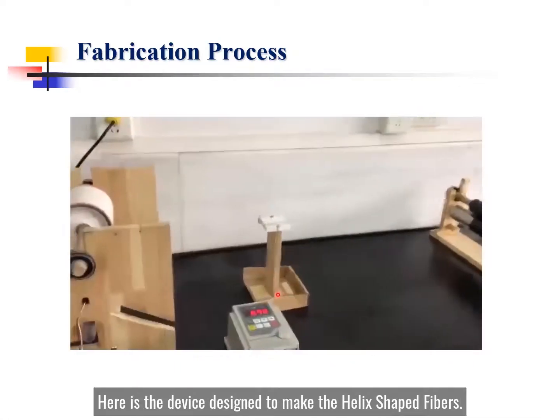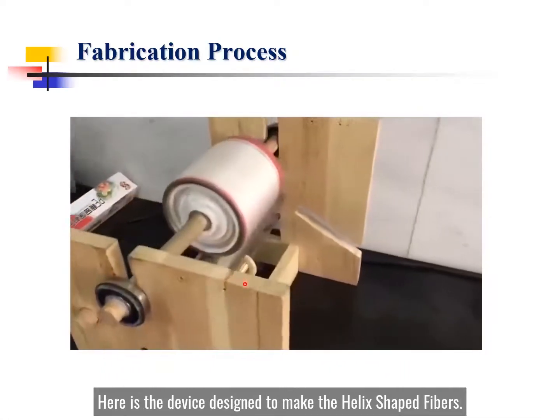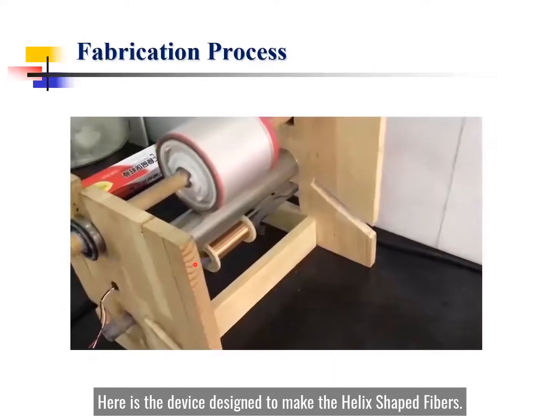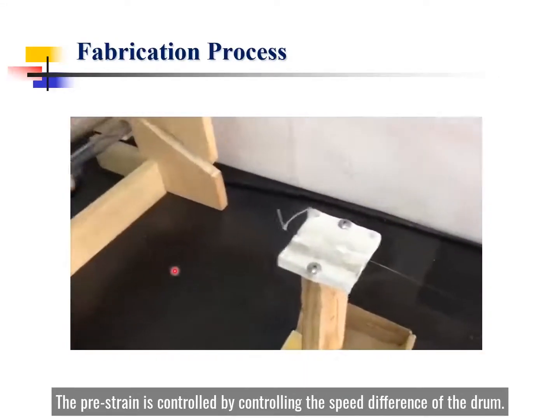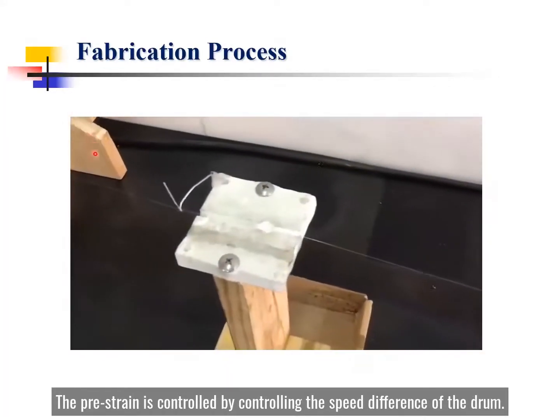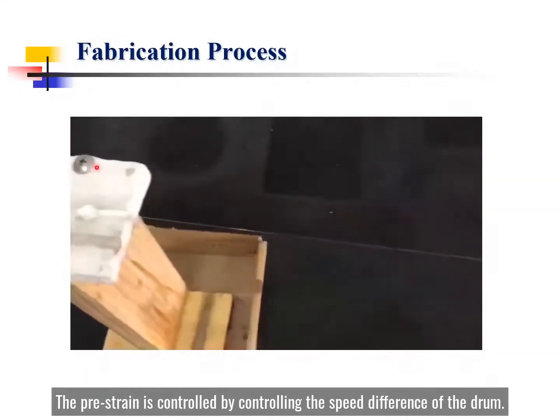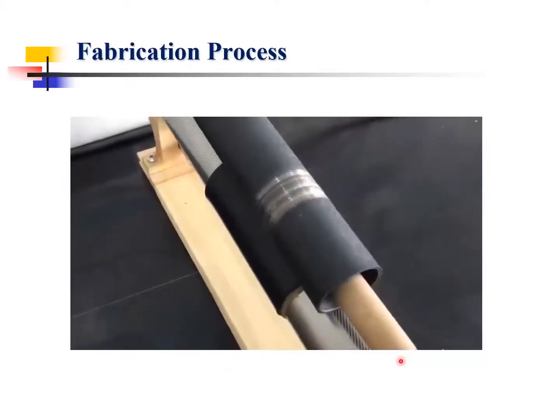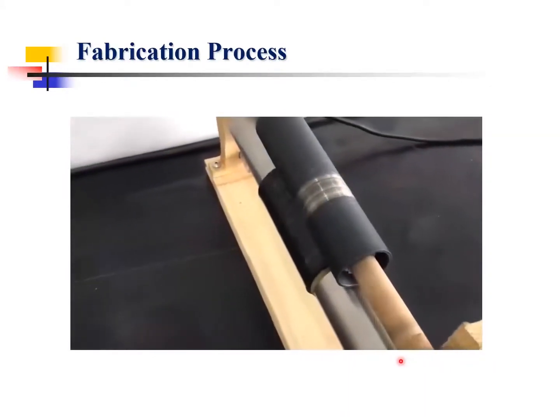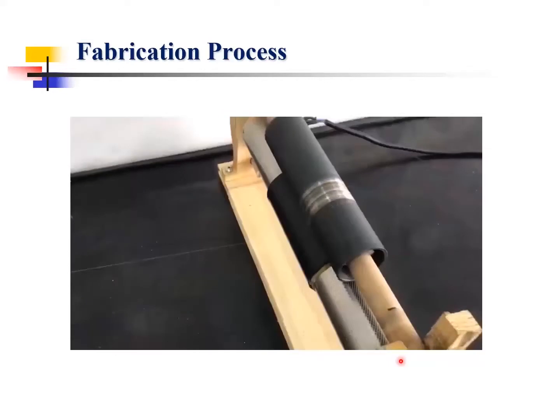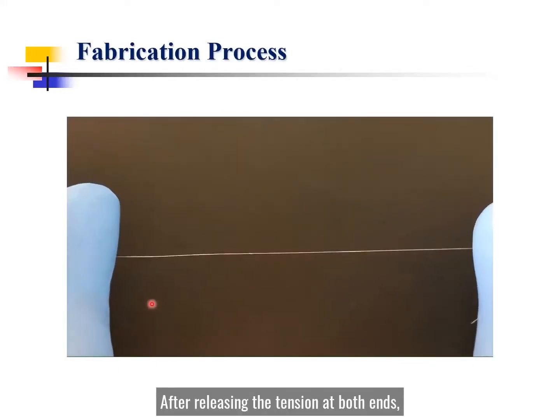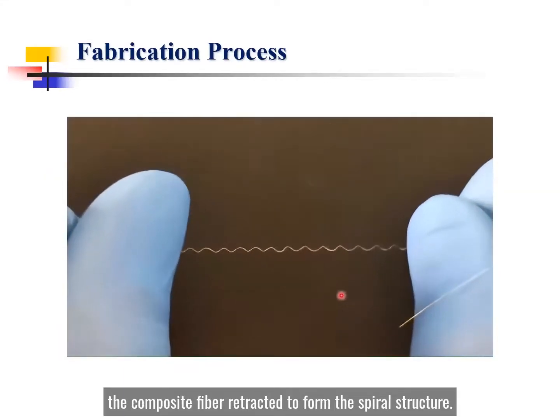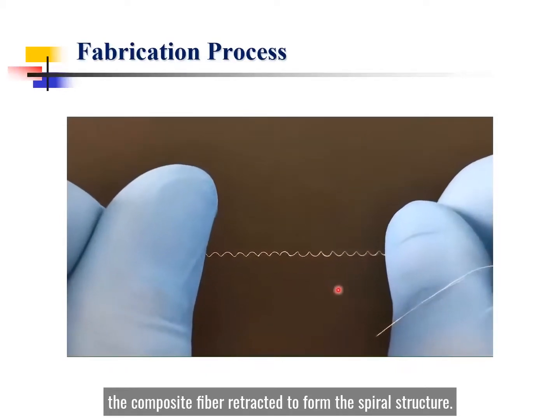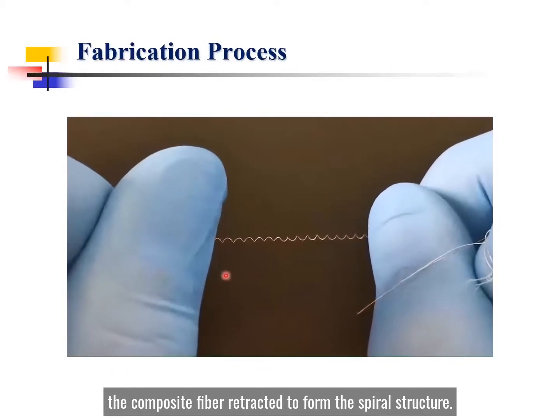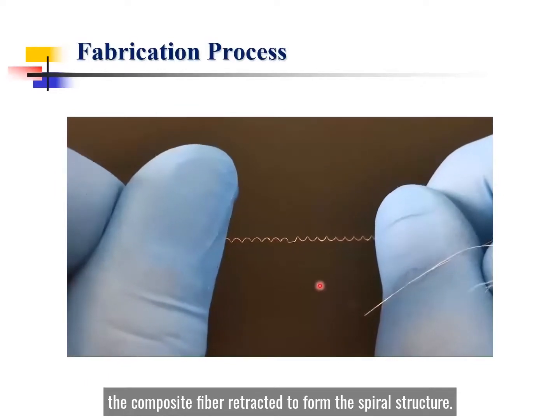Here is the device designed to make the helix-shaped fibers. The pre-strain is controlled by controlling the speed difference of the drum. After releasing the tension at both ends, the composite fibers retract to form the spiral structure.